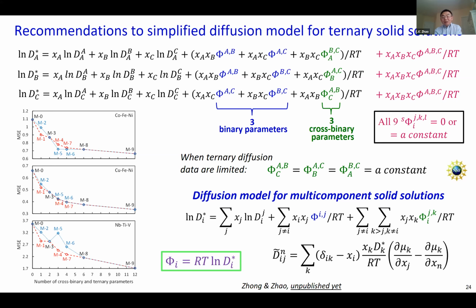So if we just use this simple model, if you have very little data, then you just use model M1, just introduce this one as a constant. I think this is a very robust model. I can easily extrapolate using the Anderson-Ågren treatment for the mobility to multi-component systems. So we believe this is going to be really useful, and very few systematic studies like this have been carried out before.